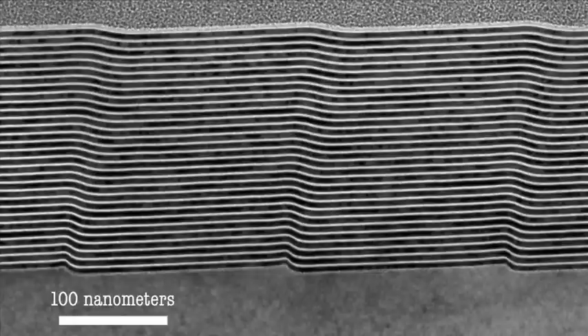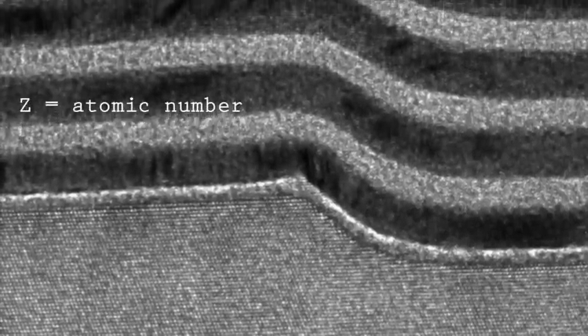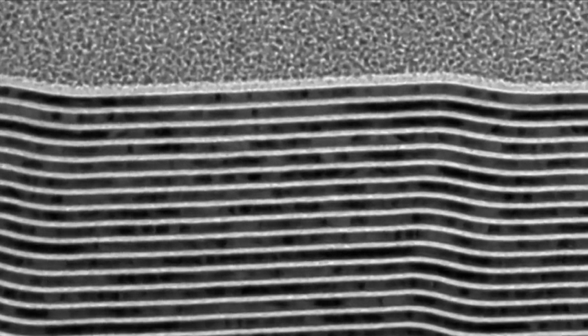The second major innovation in this work is that if you want to make a super-efficient grating, you can't do it with a single surface. What you need to do is make multiple gratings which lie on top of each other — a three-dimensional grating, not a two-dimensional grating. Once we'd formed an essentially atomically perfect substrate, we evaporated a low-Z material and then a high-Z material, alternating, until we'd formed a three-dimensional structure. The trick was figuring out how to replicate that perfect surface, so the hundredth layer above it is also still perfect. These two aspects together — atomically perfect grating and three-dimensional replication — led to an entirely new type of grating, and this was the origin of the patent.